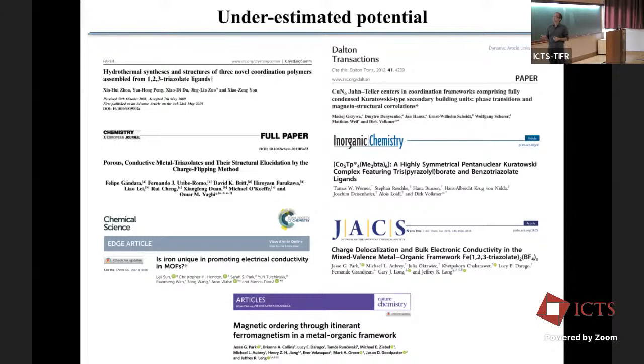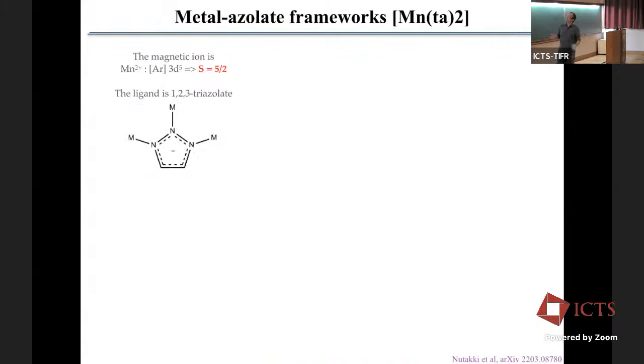properties of this structure. And so to do that, we're going to start with manganese magnetic ions and with the triazolate ligands. So manganese ions, why do we consider manganese ions? Because manganese 2+ has a half-filled 3d electron valence band, which means you have a magnetic spin S equal 5/2. So 5/2 is pretty large. That's, to a good approximation, a classical spin. And it's a half-filled band, which means that your system is roughly isotropic. So considering Heisenberg spins will be a good approximation.